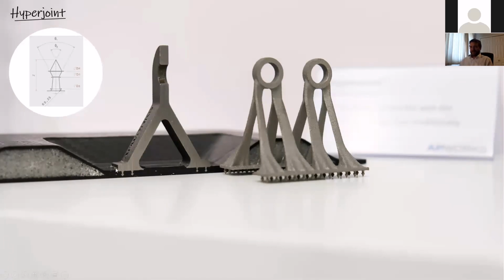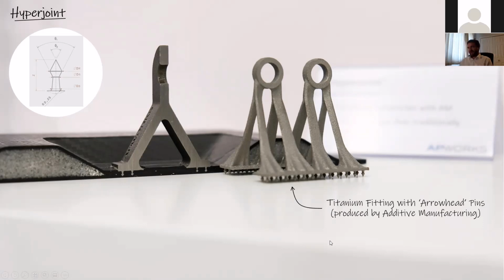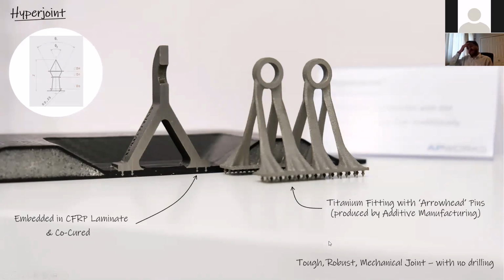Now, for those of you who are maybe scratching your head at how do you get the pins in there, if you haven't got direct experience with composites manufacturing, the obvious thing is you have to embed these before you cure the laminate. So in general, we're working with pre-preg materials. So that means you've got fibers in layers, and those fibers are already impregnated with a resin, which is still soft. It's tacky and sticky, but it's still soft. And you're laying up the laminate and then embedding the pins in and then curing it in an autoclave generally. And that's then making it go hard and locking those pins in place. And what you create is a tough, robust mechanical joint without drilling. And that was our objective.